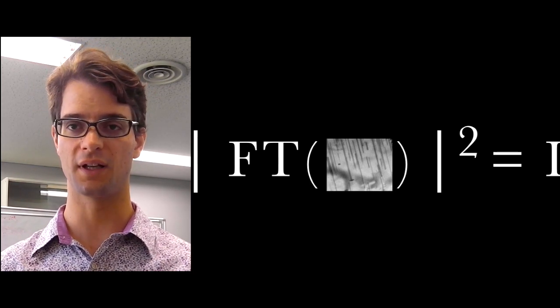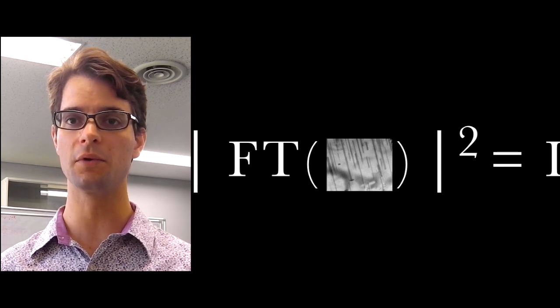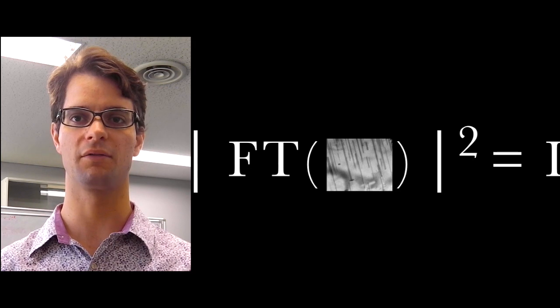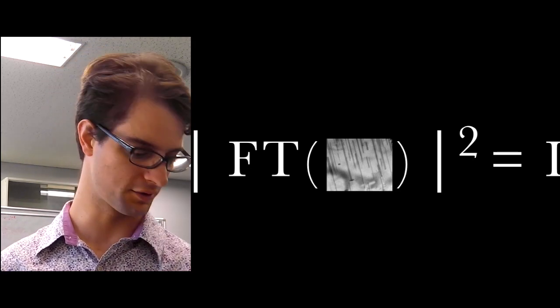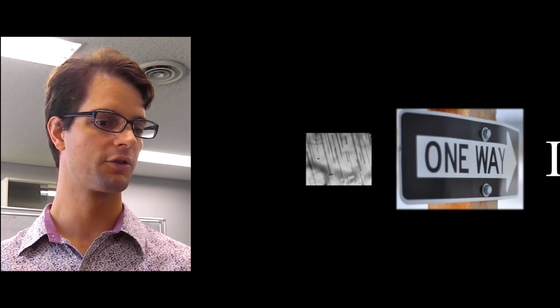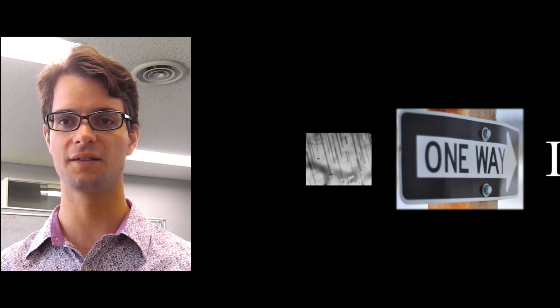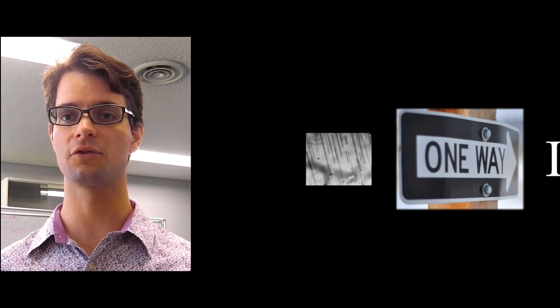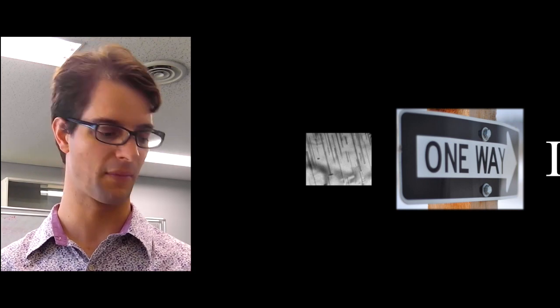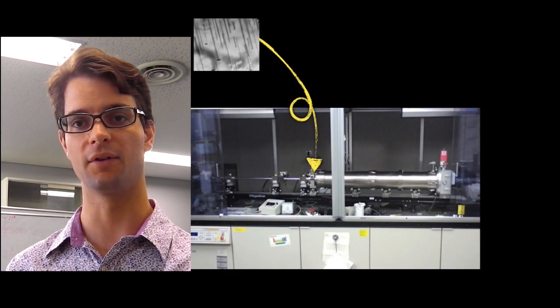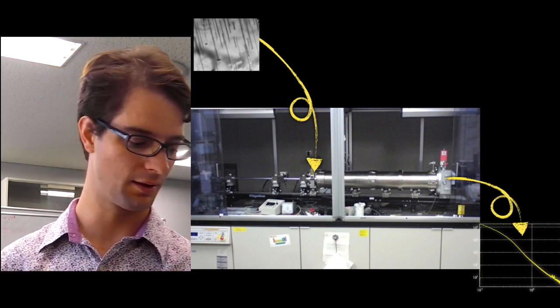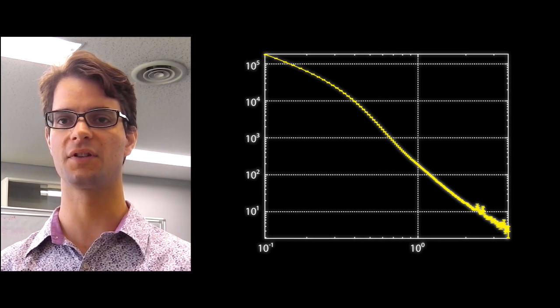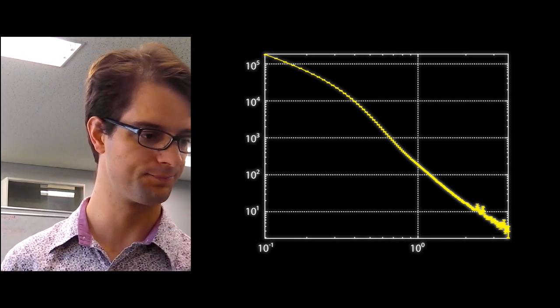Unfortunately, however, we're not seeing the entire Fourier transform, we're only seeing the intensity component, which means that we've lost essential information in this process. And this information loss is the reason why this is strictly a one-way process. So by collecting the scattered intensity, we cannot uniquely retrieve the electron density structure that is inside our sample. And this is one of the reasons why many people are having so many problems when they measure small angle scattering patterns to try and extract physically relevant information from small angle scattering.